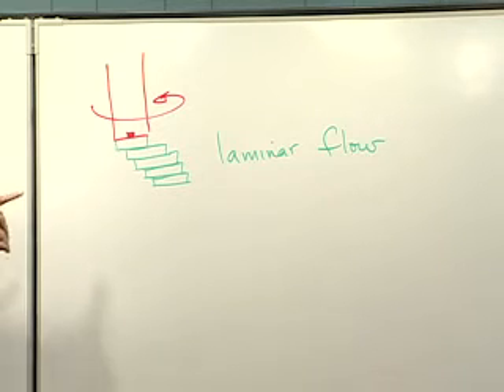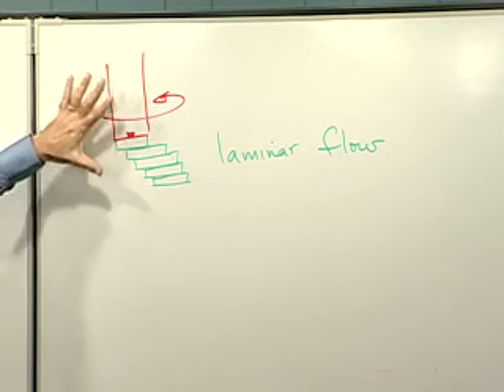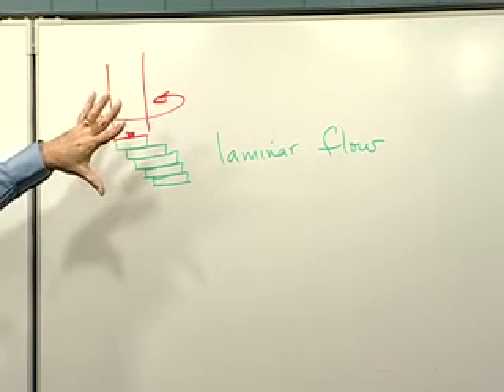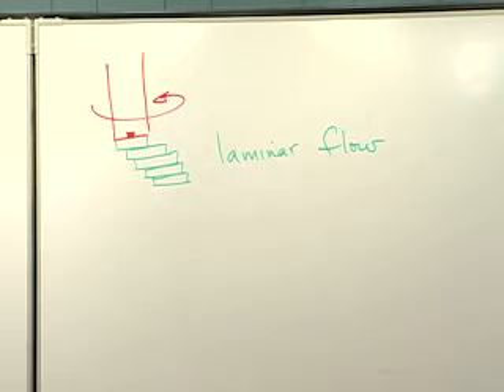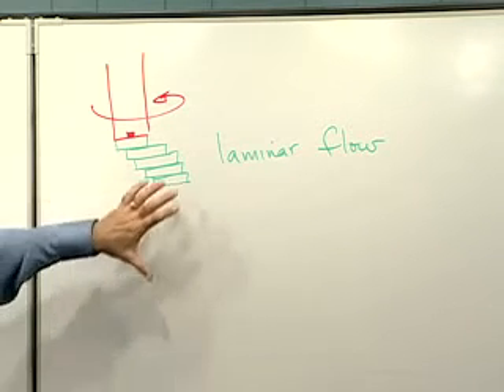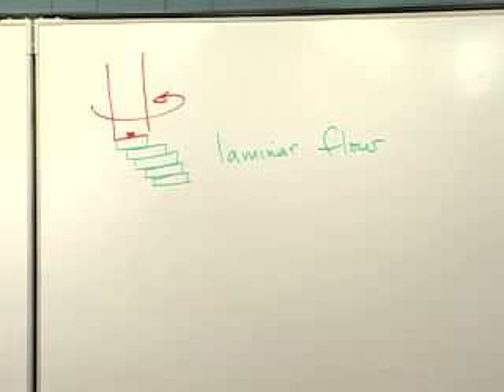You're going to have two problems with that. We never did it. Number one is you will exceed the Reynolds number of this solution if you do that, so it doesn't matter that you can rotate at 2,000 RPM. Second, those VW engines didn't exactly run super smoothly, so you will exceed the Reynolds number quickly because of the vibrations that you're going to introduce into your cell. So you want to have a situation that looks like that. Which means you can get up to something around 1,000 RPM, if you have a nicely polished electrode and everything is perfectly flat there.